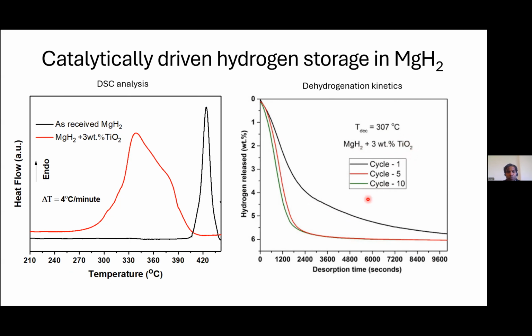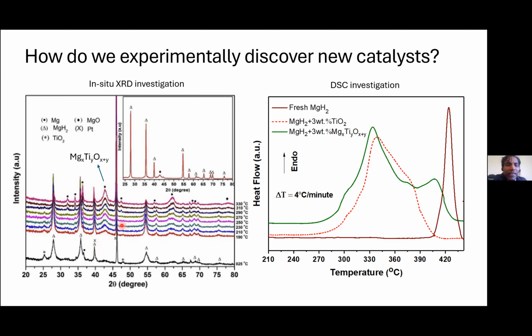Now we are thermally decomposing this material. While you thermally decompose, titanium dioxide disappears. That means this is chemically reacting. All the other phases, we evaluate carefully, and there is nothing surprising because magnesium hydride transformed to magnesium, that is fine. But what is surprising is the moment titanium dioxide disappears, another very interesting phase is forming. That is later on identified to be titanium-dissolved magnesium oxide rock salt. This is the active species.